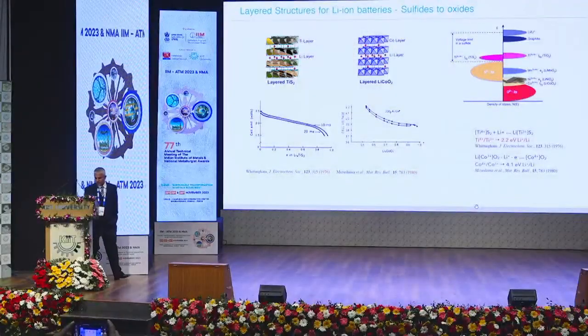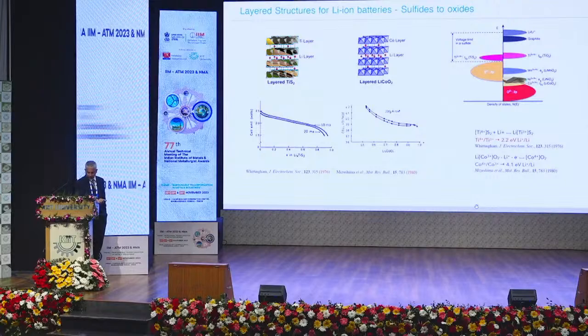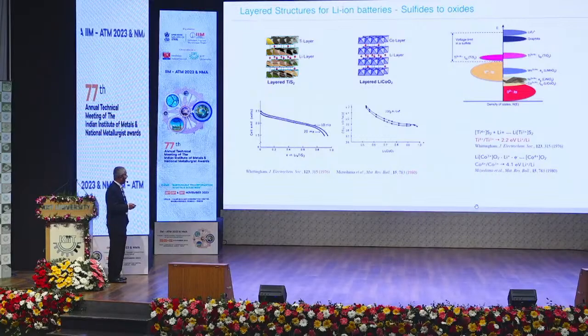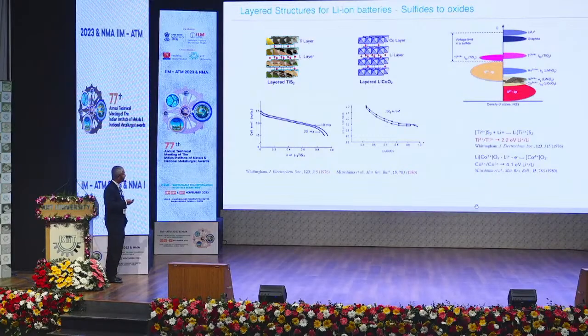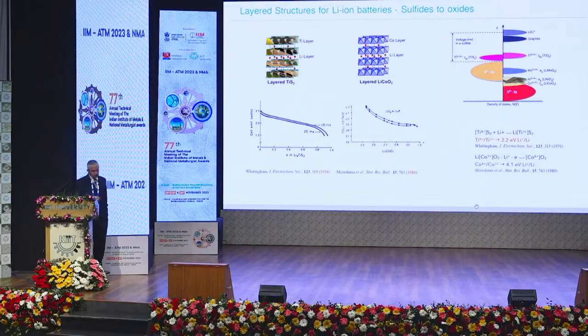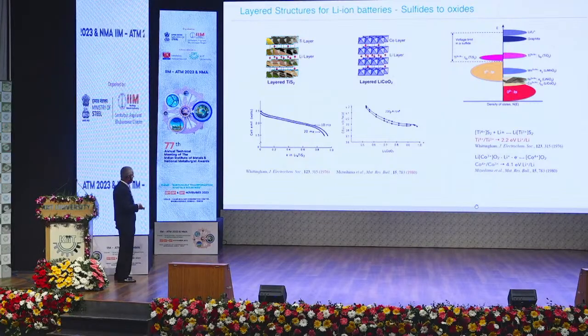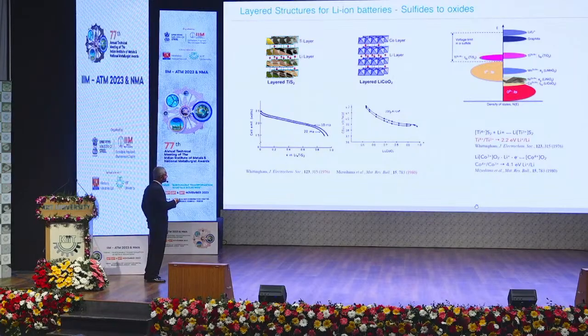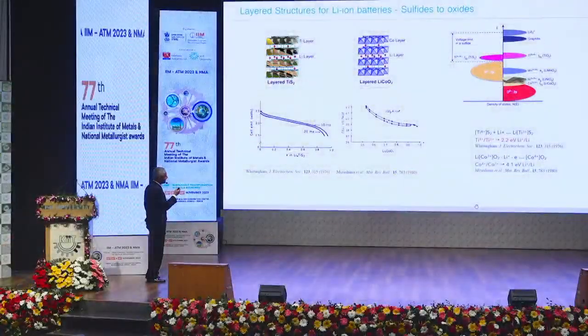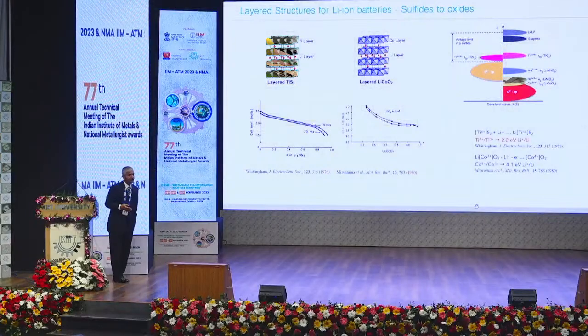Although it was interesting, 2.2 volts was not very much higher than alkaline batteries, and with the use of lithium metal, we did not have an appropriate anode to make a proper lithium-ion battery. In 1980, Professor Goodenough's group, Mizushima, identified that if we exchange the sulfides for oxides, we could get a lot of these energy bands, and we can find a lot of materials that might be useful.